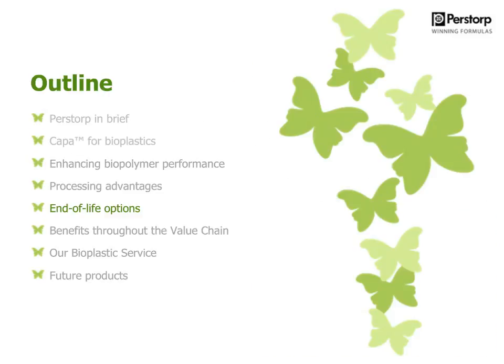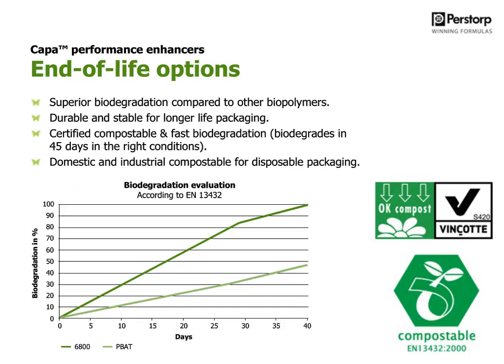And so, as I've mentioned a couple of times, it's a biodegradable polymer, and now we will look into the end-of-life options of these grades. We have tested according to the standard EN 13432 at a test institute here in Sweden to have the test results and the proof to be able to show that it actually is compostable. And so this we have done, and with that test we can actually show that within 45 days, under the right conditions, it's 100% biodegradable and compostable.